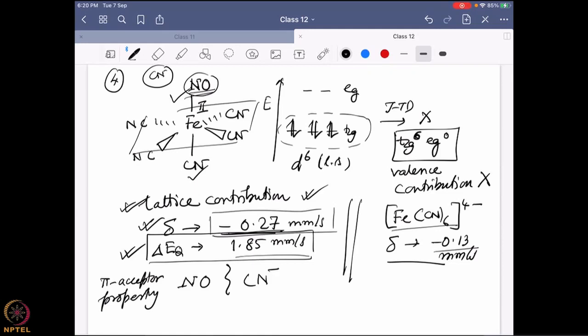So why is it more negative? Go back through your logic. That means it is going to have a higher value of s electron density at the nucleus. The psi zero squared value is higher. That means it has more s electron interacting with the nucleus. That means it has less shielding effect. That means it has less d electron. So how can it happen? It can happen if nitrosyl is pulling out more d electron compared to cyanide. So by comparing that, keeping all the other things the same, pi acceptor property wise, nitrosyl is actually a little bit better than cyanide in this particular scenario. And that is why the delta value is moving towards a more negative side.